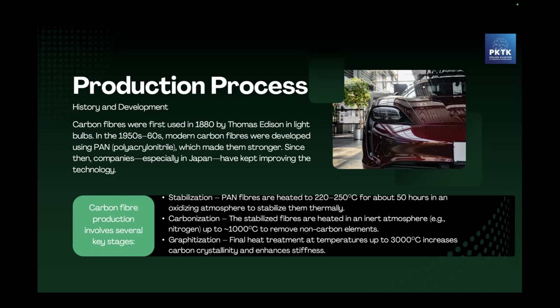Then the next step is the carbonization. The carbonization removes non-carbon elements from the carbon fibers, and the process is realized at a temperature over 1000 degrees Celsius. And the last step, also very expensive, is the graphitization, the final heat treatment at a temperature over 3000 degrees Celsius, which increases the carbon content and, of course, stiffness.